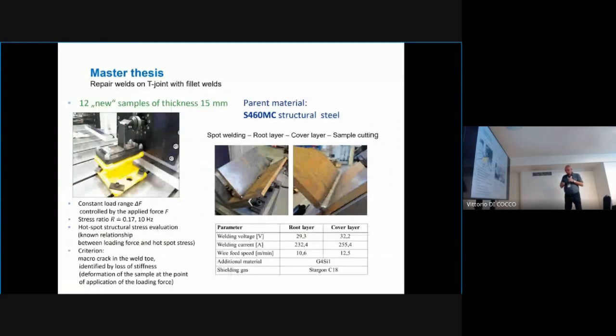Now to the master thesis. We use again our test stand. We use the T-joint with fillet welds. As a parent material, the structural steel S460MC was used. Again, here is some information about the welding process. We loaded the test specimen with a constant load range controlled by applied force. This is a stress ratio near 0.17 with 10 Hertz. It's very easy to measure by strain gauges or calculate the stress ratio for this type of loading.